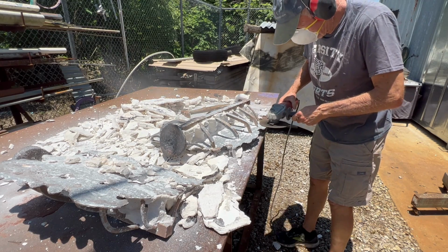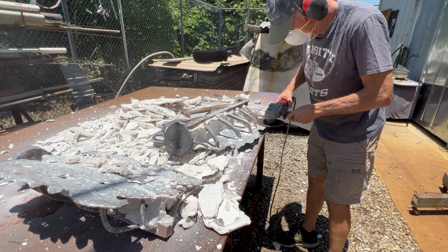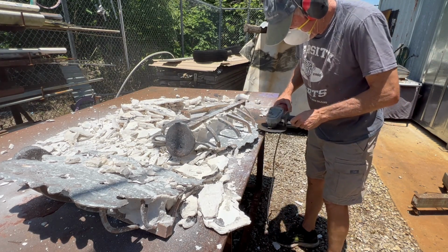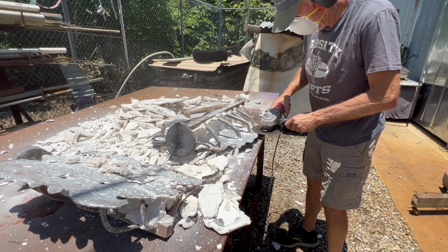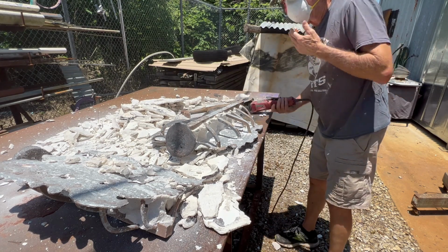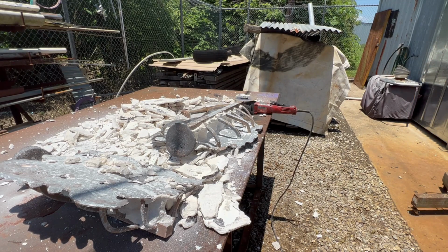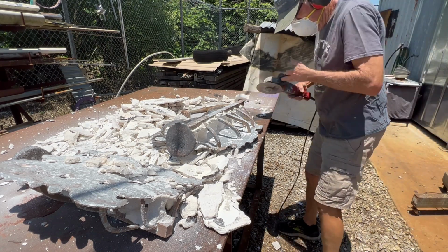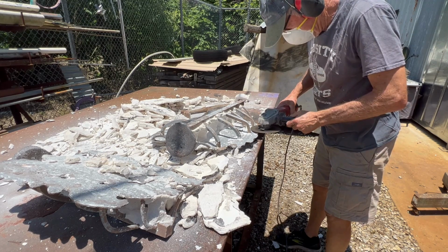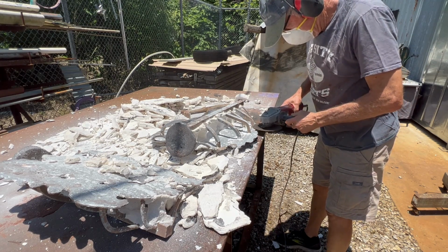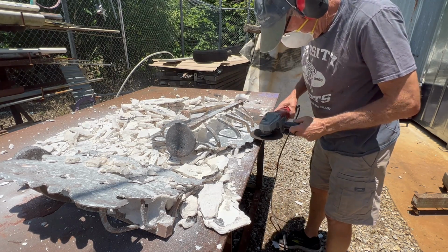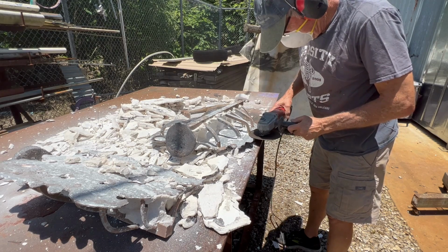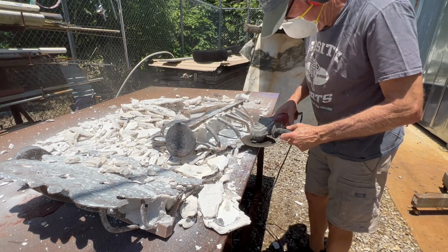So why did we get a void where the bronze didn't fill the mold at the top little upper corner? Obviously, it was temperature related because the bronze froze before it flowed all the way. In the words of my grandson, who is 4, I don't know. Could have been that the bronze wasn't hot enough. Could have been the molds weren't hot enough. Could have been I poured too slow. Could have been this was the second one I poured, and by that time we had lost another 50 or 60 degrees of temperature.